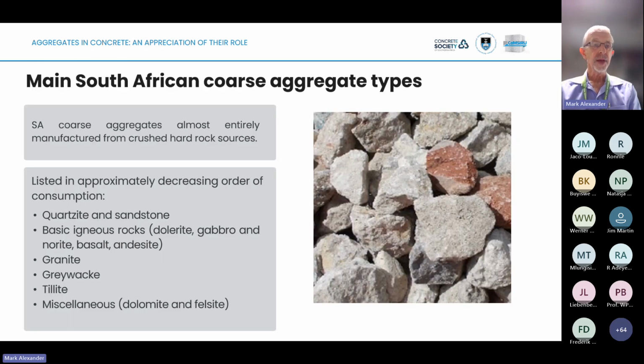Now, let's have a think about the main South African coarse aggregate types. And here, these are ordered. This list on the left is ordered more or less in the decreasing order of consumption. So quartzites and sandstones by far take the lead, and probably 70 or 75% of our aggregates. Then we get the basic igneous rocks, the dolerites, right down to the andesites. The interesting one here is the basalt from the Lesotho Highlands, which, if you've ever worked in the Lesotho Highlands, you'll know is quite a problematic rock, and one has to be extremely careful of that one.